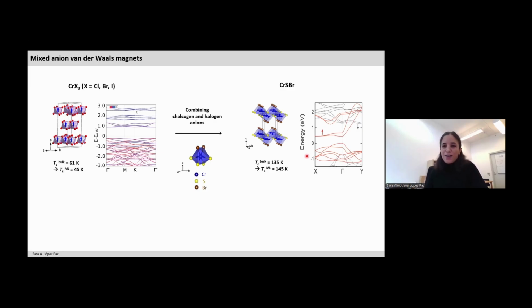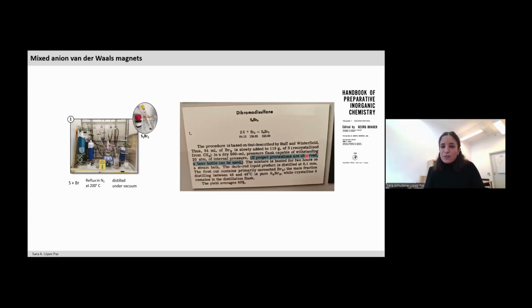And for this, we went to the literature. And we found that one of the proposed approaches was to use disulfur dibromide as a transporting agent. And apparently, this is a very robust synthetic procedure. I have to say, we did not follow the procedure by heart, but we used a conventional round bottom flask. And after reacting the elemental sulfur and bromine and distilling the product under vacuum, we could isolate our transporting agent.